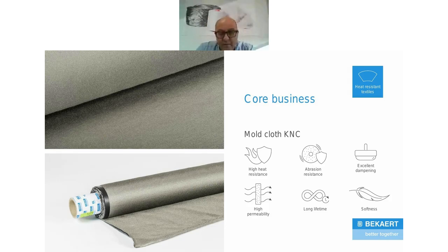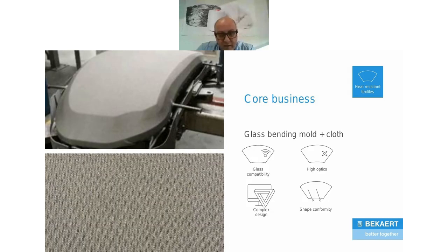So it's important that this permeability is quite important to have a soft contact between your cloth and the mold. And if we look at the most important features for this glass bending and the mold covering of a cloth: again, the glass compatibility, so inner and outer should have the same shape, and then also the high optics, which is important, optics in transmission, optics in reflection, and it should also be very stretchable to cover complex designs of the mold.